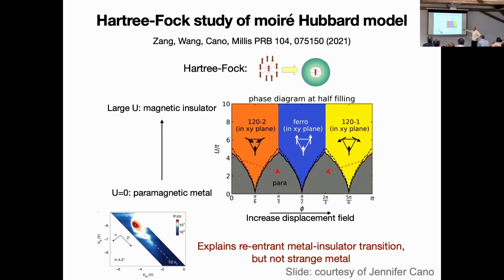If we are at phi equals 0, which is the standard triangular lattice, what Hartree-Fock tells you is that there is a metal-insulator transition in this system, from a system that has no magnetic order to a phase which has the famous 120-degree spiral antiferromagnetic order characteristic of the triangular lattice. We actually know better. We know that here there is a spin liquid phase, or at least a different insulating phase. I'll show this to you in a few slides. But now this is just to illustrate the fact that phi, the displacement field, gives you an additional handle.